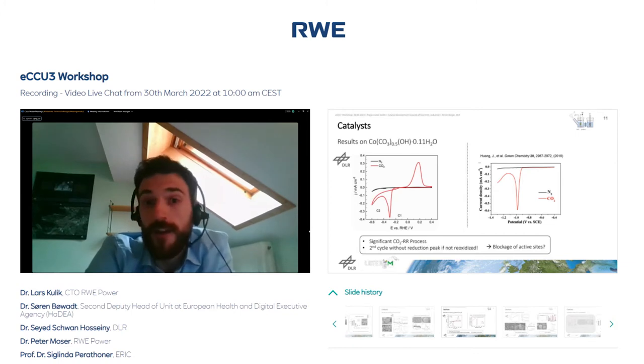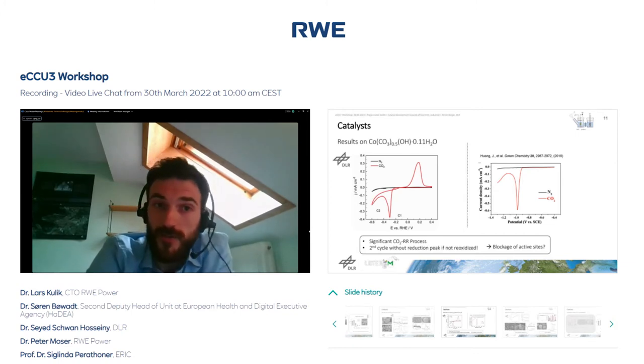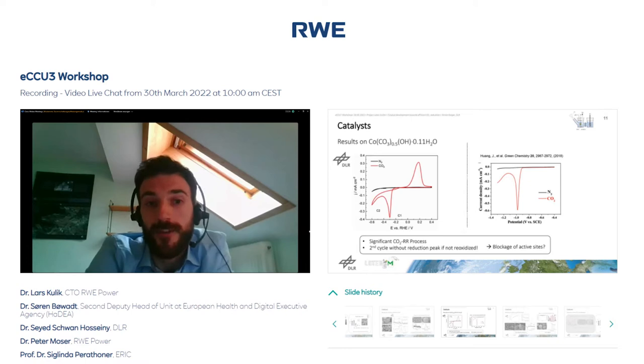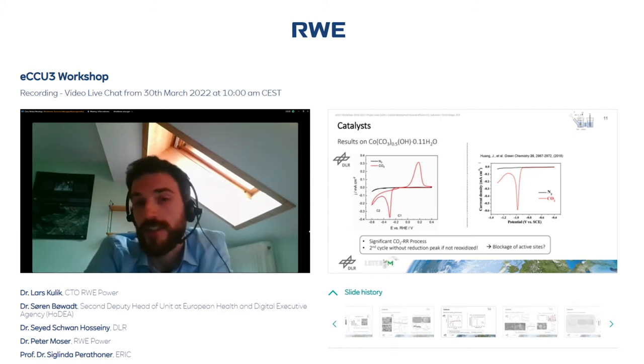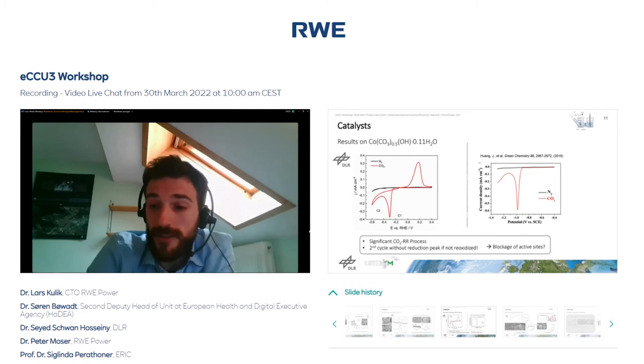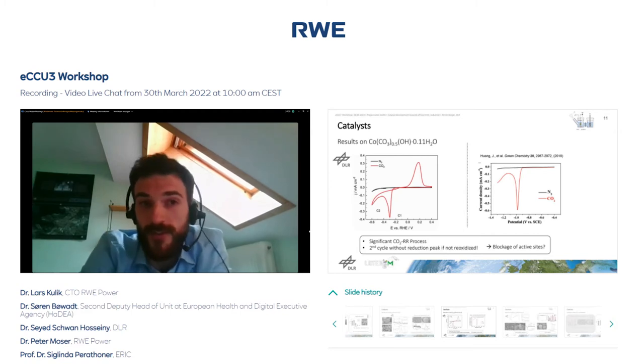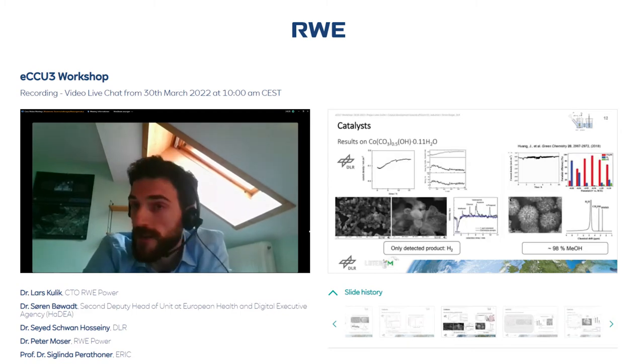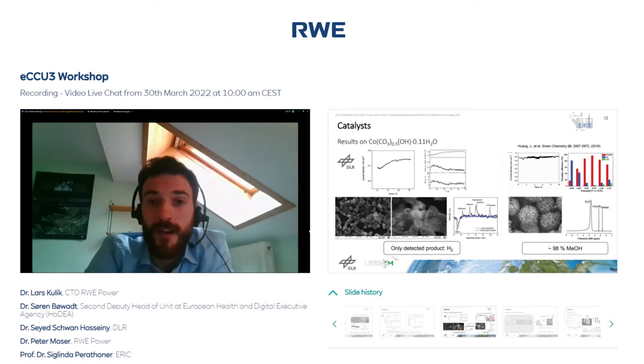This could be recovered in case one goes to a very oxidative environment, like shown here on the right side with this oxidative peak. Then the reductive peak would come again. But this was not discussed and shown in the paper, but could be the reason for this result that is shown on page 12 now, a comparison of the analytics on the left side, also pictures of the SEM